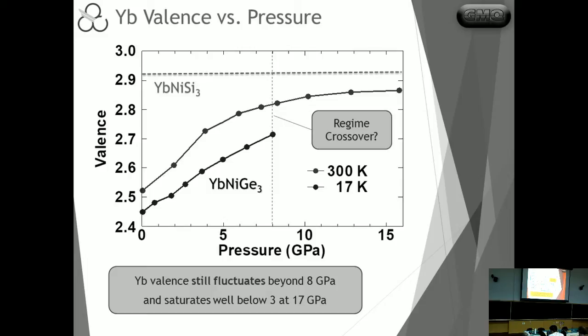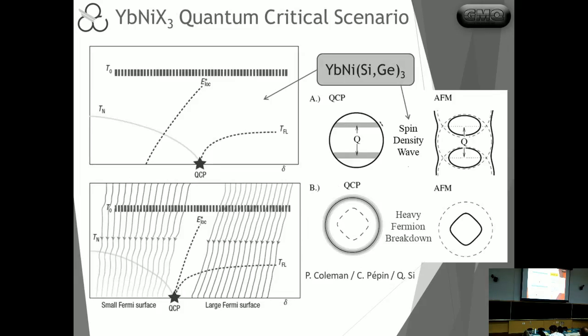In this case, it just remains there around 2.92. But the important aspect here in terms of quantum criticality is that we can clearly see in the case of the Germanides that as we reach the quantum critical point, as we cross it, we still have very significant valence fluctuations of the ytterbium here. And this has implications in terms of the type of quantum criticality that is observed in the system.